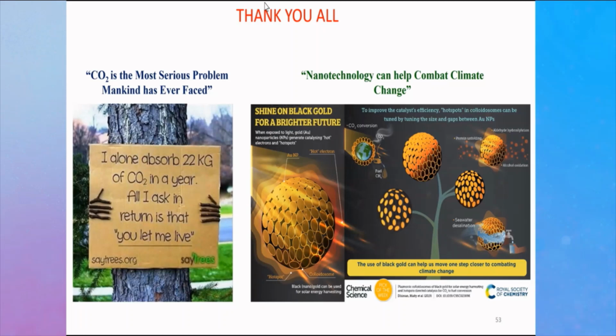Kaushik Goat asks: what is the stability of black gold with respect to the cycle number? They are very stable because they are sitting on the silica surface. They are very stable for the various cycles that we did. We did up to 10 cycles and nothing happened.